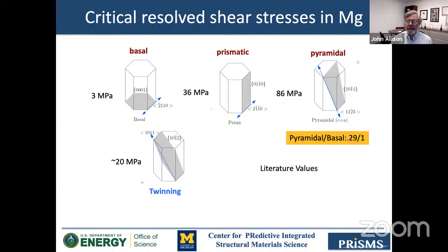So this balance, or this ratio of pyramidal to basal slip, is a very important parameter. The higher this is, the more difficult, obviously, it is to get pyramidal slip, and this can lead to ductility problems and formability problems because of slip anisotropy in general deformation. And so the literature has suggested this is about a ratio of 30 to 1, 29 to 1. And we think this is pretty reasonable from the literature.